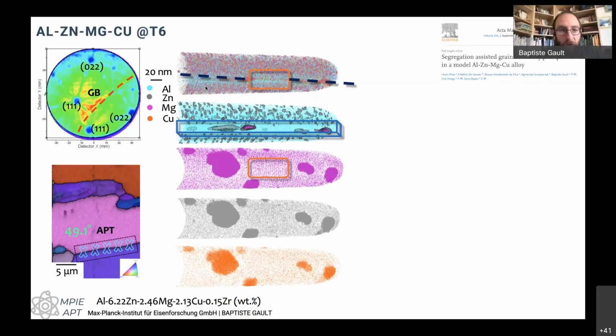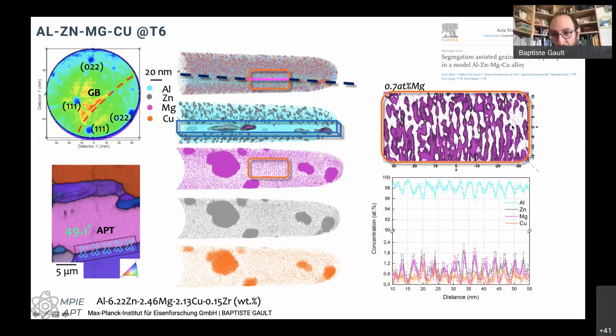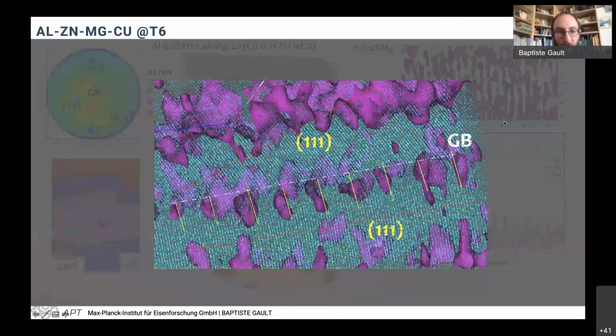And in this case, we actually could find some compositional fluctuations with a period that corresponded to 111 planes, and it actually happened to be a sigma 11 grain boundary that we took more or less at random, so we're quite lucky. But we can get to that sort of level of information with the atom probe when we start digging into the data.